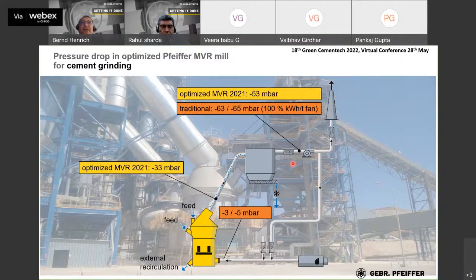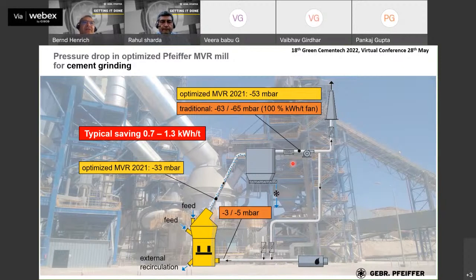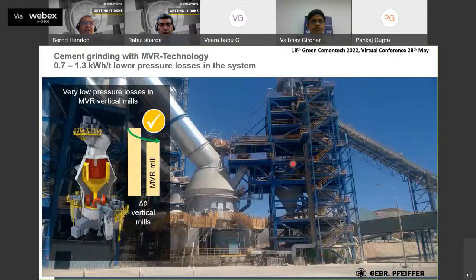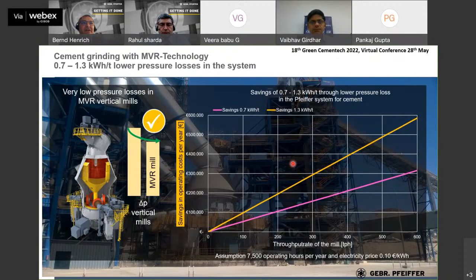That gives you roughly 1 kilowatt hour per ton saving in the cement grinding, which, compared to the overall power consumption, is maybe a small step, but 1 kilowatt hour per ton, again, this is a saving effect. And that means the vertical roller mill grinding system becomes even more efficient compared to the combi grinding or the finish grinding in other grinding systems. And it provides you saving of electrical energy, saving of costs, and finally, reducing the CO2 footprint of the complete plant.